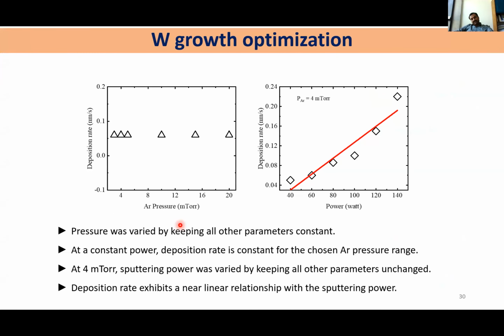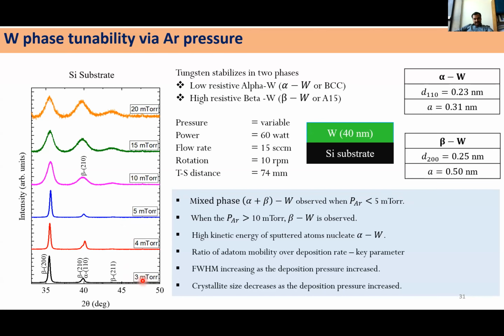Okay, so here we wanted to work with argon pressure. As you can see here, when we change the argon pressure in our sputtering deposition, the deposition rate did not change much. And when we increase the power, it is almost a linear increase in the growth rate. Okay, so we have changed the argon pressure, and an interesting thing we have seen, at a constant power, right? We fix the DC sputtering power to 60 watt. At 3 mTorr, 4 mTorr, 5 mTorr, we are getting a mixed phase tungsten, above which we are getting a pure beta phase. Okay.